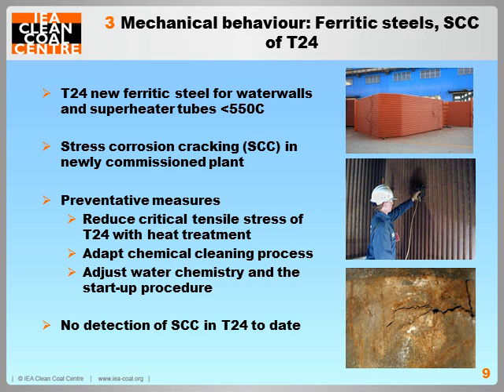T24 is a new ferritic steel developed in Europe for ultra-supercritical power plant. Shortly after first commissioning in 2010, multiple cracks developed in T24. Evaluation found the cracking mechanism to be stress corrosion cracking. Preventative measures such as additional heat treatment during the welding procedure, adjusted water chemistry, adaptive chemical cleaning process and startup procedure were introduced in 2011, and to date no stress corrosion cracking has been detected.